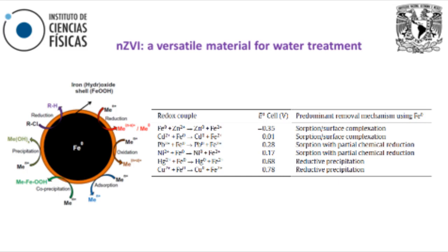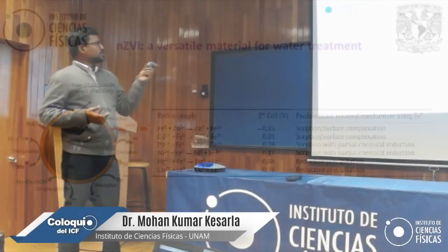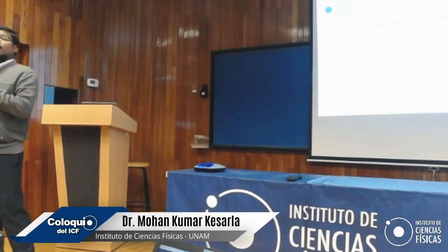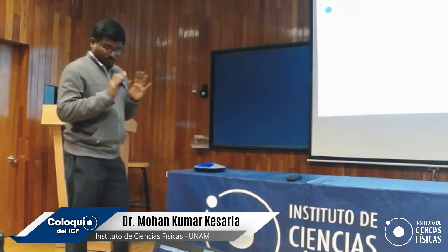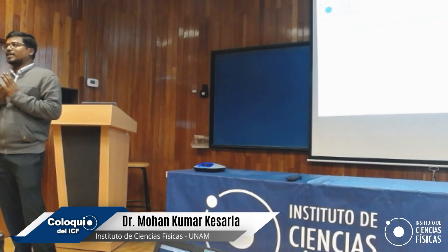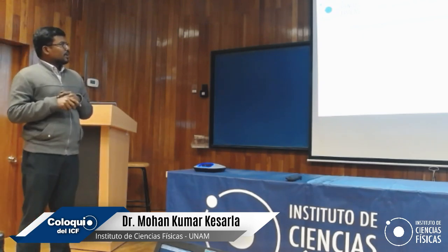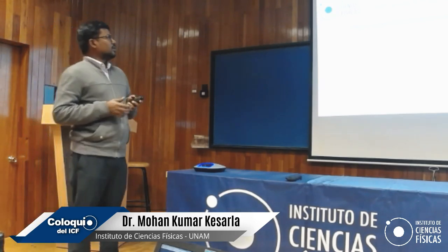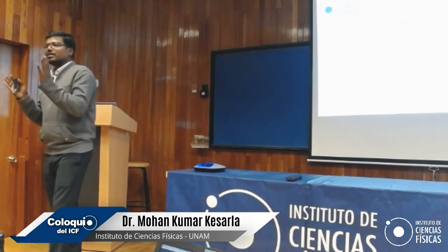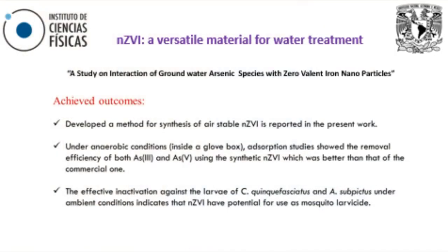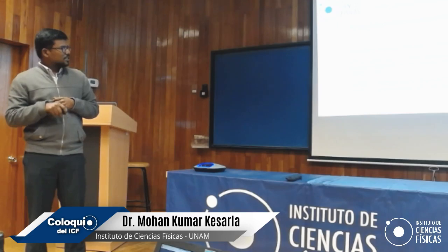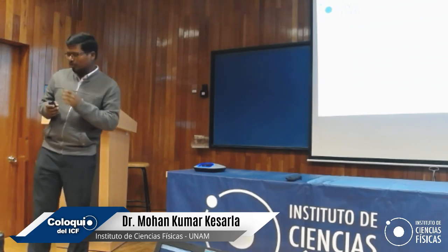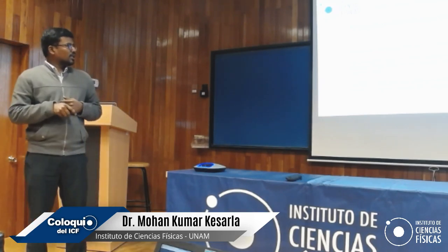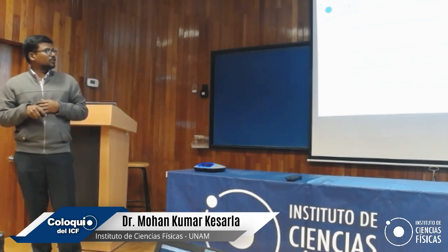So what we did in this particular area, we studied the interactions of groundwater arsenic. Arsenic is one of the deadliest species in water, and both arsenic 3 and arsenic 5 are very bad; even in Mexico, many sites were contaminated with arsenic. So we studied the interaction of groundwater arsenic with zero valent iron. We developed a method to bring about stable zero valent iron, and then under anaerobic conditions we checked the adsorption capacities for arsenic 3 and arsenic 5, and worked out the exact mechanism behind how they are getting decontaminated. And the third thing is, using the same zero valent iron, we controlled the larvae. The stage before the mosquito is the larva, and we controlled the larvae in water and tested against mosquito larvae also.